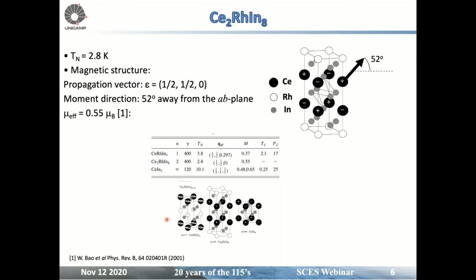all the other members of the family. So we see that CeRhIn5 has propagation vector (1/2, 1/2, 0.297), so it kind of becomes... the 218 and 115 keep some of that behavior. So all of them have magnetic structure with propagation vector (1/2, 1/2, something), and 115 is incommensurate, and the 218 is a commensurate magnetic structure with (1/2, 1/2, 0).